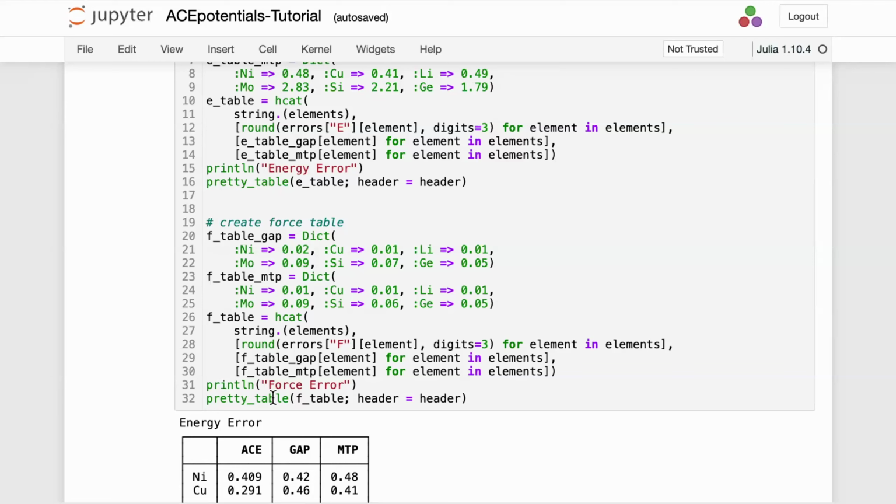This is purely empirical. Yeah. So in specific scenarios, it might be a really good idea to do this. For example, you want the repulsion as atoms get close to be perfectly right. You might want to subtract the ZBL potential, and the difference between DFT and ZBL may well be a good thing. I'm not certain about this because DFT doesn't behave like ZBL as atoms get close, but that's the gist of the idea. So if you know there are specific features in the potential, you could remove them. Specific difficult features.